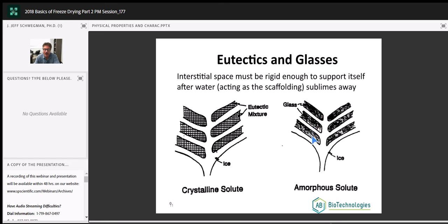The glassy phase, however, here in the interstitial space has a high water content. That's unfrozen water that's bound in there or locked in that glassy phase. Much more difficult to get out here than it is in a crystalline eutectic phase.